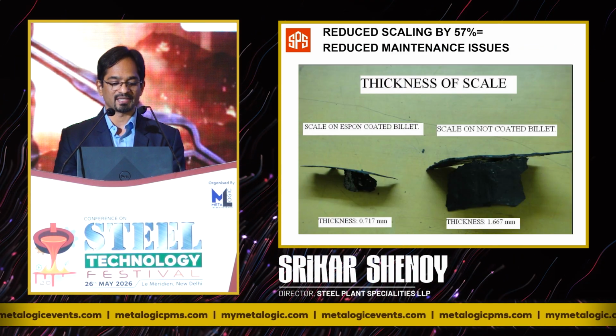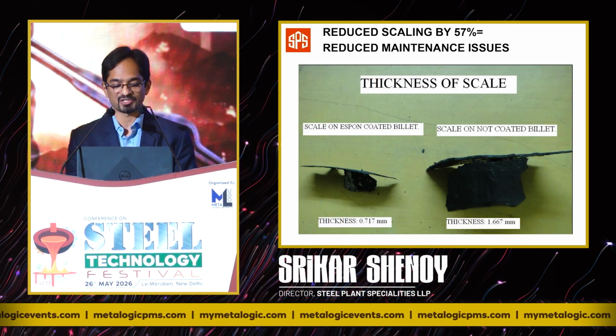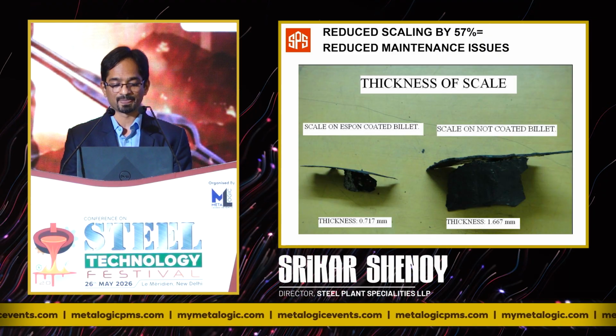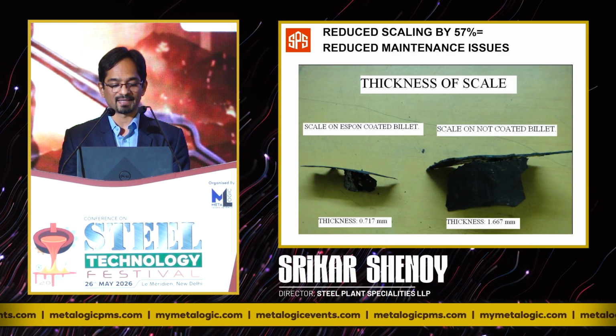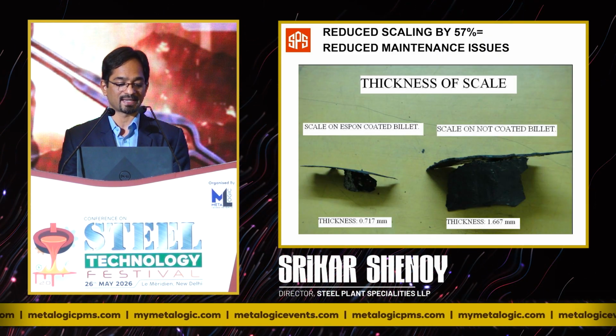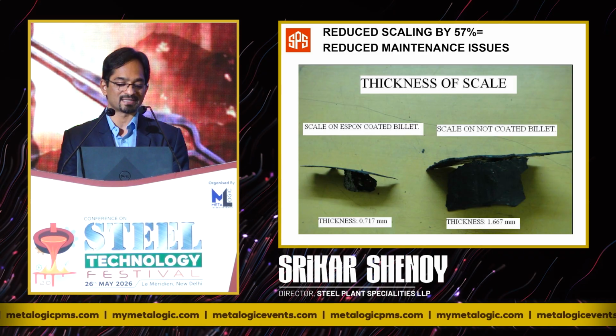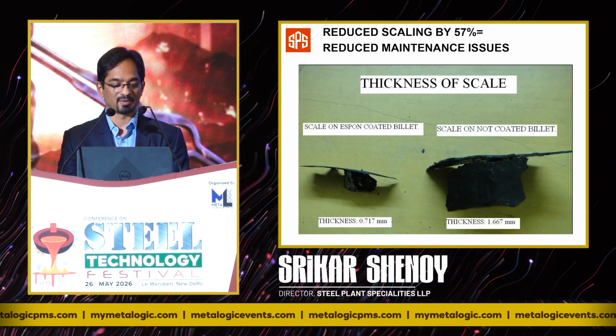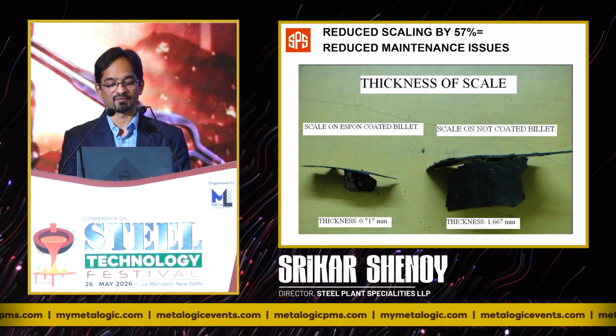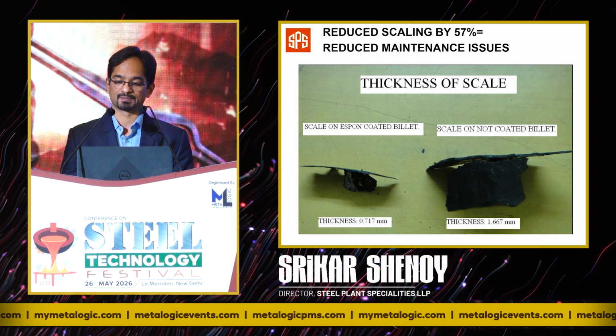And what you're seeing here is scale thickness that is measured from both the billets that I showed earlier. The not coated billet has 1.66 mm thick scale, and the coated one has 0.7 mm. You can appreciate visually also. That's again a 57% reduction in scaling.